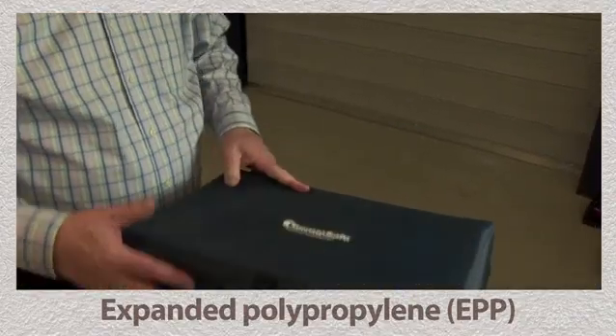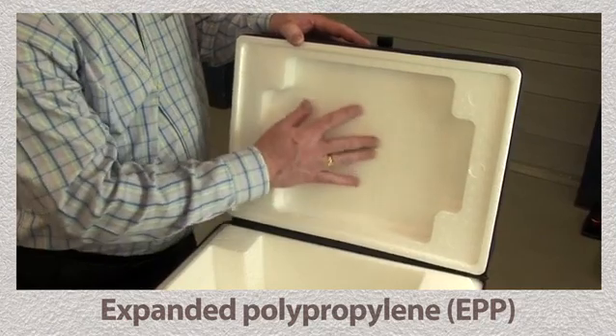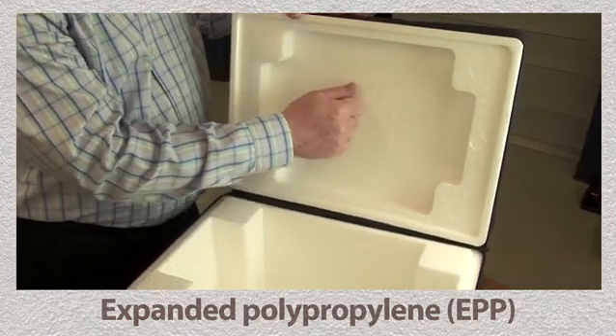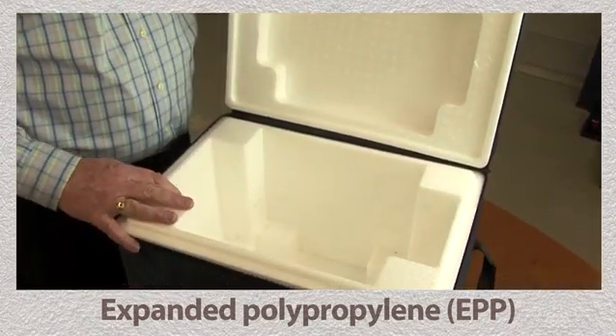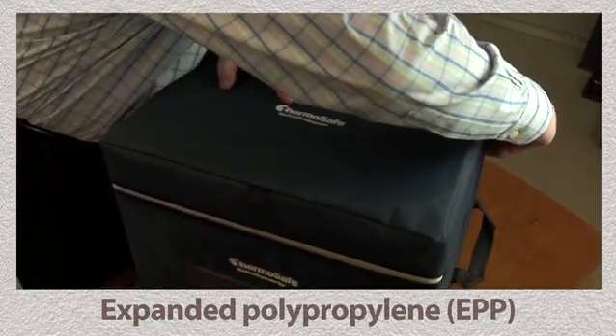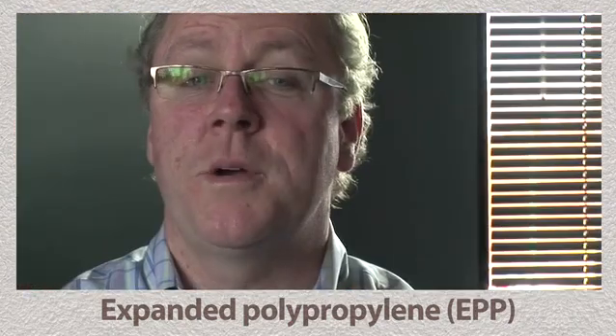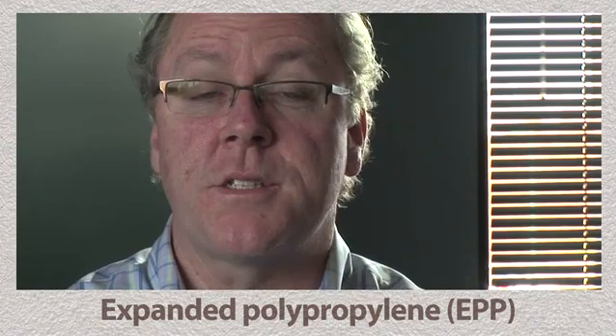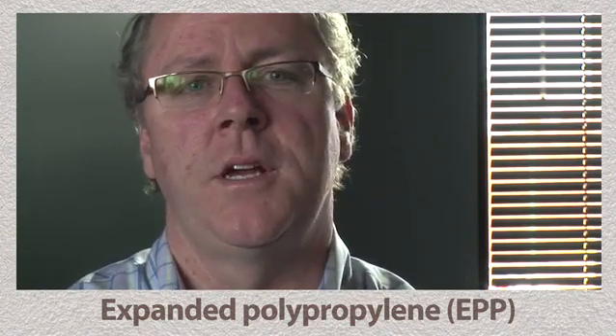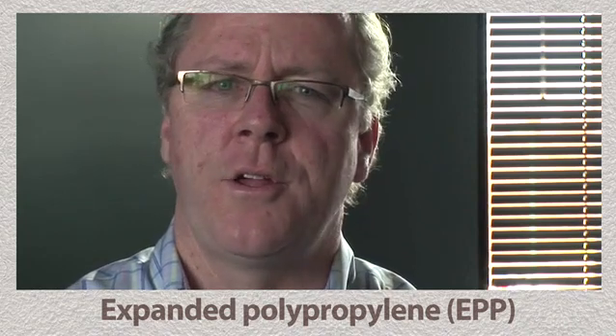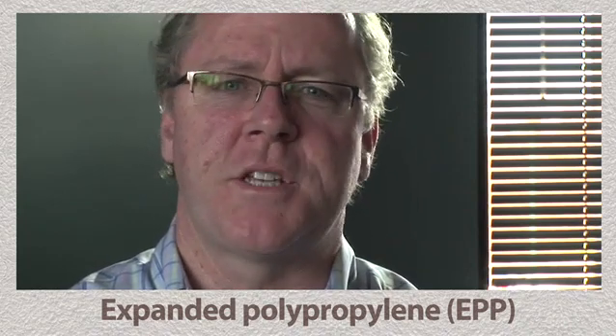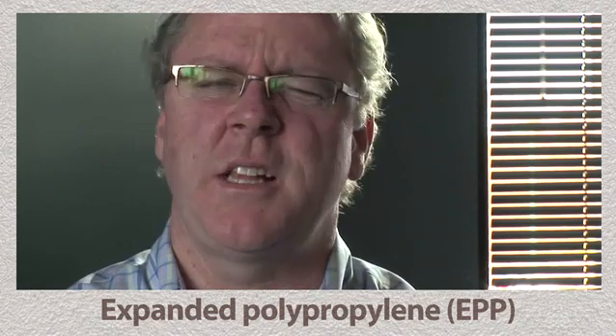If we were to go up the line in terms of what would be the next best layer of protection or insulation for materials used in packaging, a common material would be expanded polypropylene. It's usually formed in a mold in the shape of a container, and by trapping air inside between the beads and inside the beads, it provides a layer of protection. We measure a material's insulation by its resistance to heat flow, or R value. EPP has an R value of about 3.5 for every 3 centimeters in thickness of material, slightly less than that of EPS.